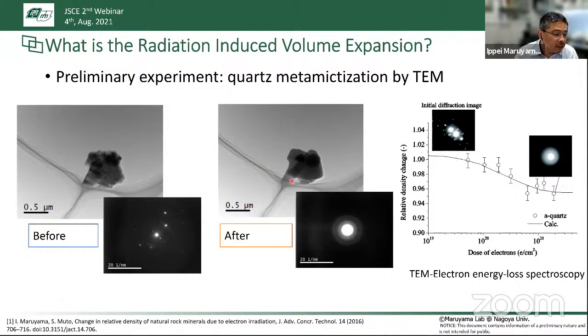And as you see, we see some difference from the previous picture after the electron irradiation. If we use electron energy loss spectroscopy, we can identify the electron density change. Based on this value, we can estimate the density change of the alpha quartz under the electron irradiation environment. And we found a 4% reduction in density, meaning about 4% expansion of alpha quartz, under the TEM observation.